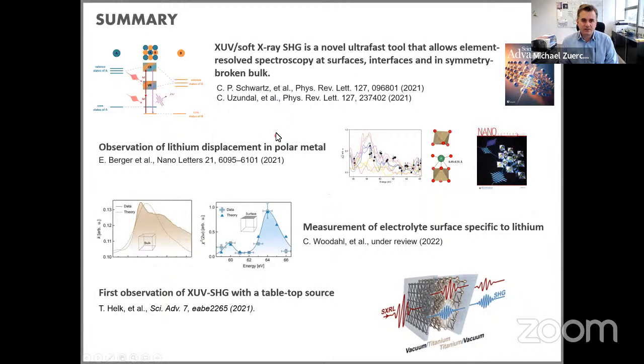So I introduced you to XUV and soft X-ray second harmonic generation as a novel ultrafast tool that allows element-specific probing of surfaces, interfaces, and also anisotropies in bulk. I walked you through one of our works where we studied the lithium displacement in the polar metal lithium osmate, and I also showed you our most recent results on studying the surface of a lithium-ion conductor. And I also showed you that indeed there is prospect to generate second harmonics in a tabletop environment.